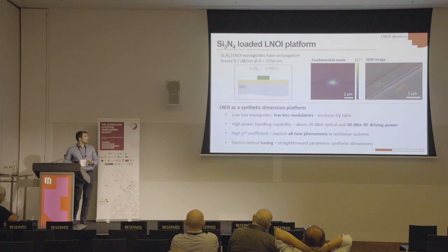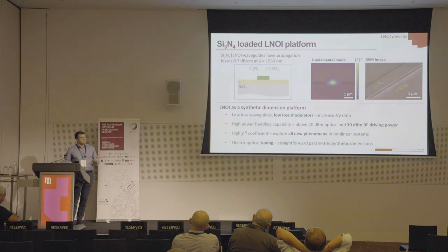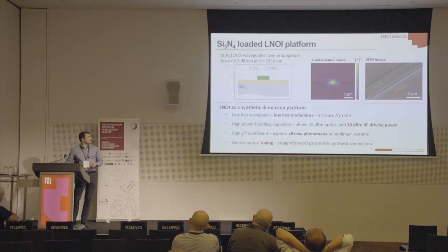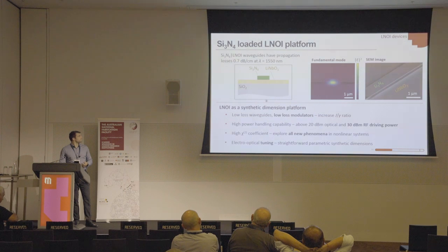So enter lithium niobate and the ANFF. If you want a modulator, there is not really anything much better you can do than lithium niobate, especially in its thin film form. The facilities at MCN and the Micro and Nano Research Facility at RMIT allowed us to develop our own process, since this is not a CMOS-standard material — a couple of years ago you couldn't readily buy a foundry service for it. We use a silicon nitride loading approach; we don't directly touch the lithium niobate material, and the waveguides are about one micron across.